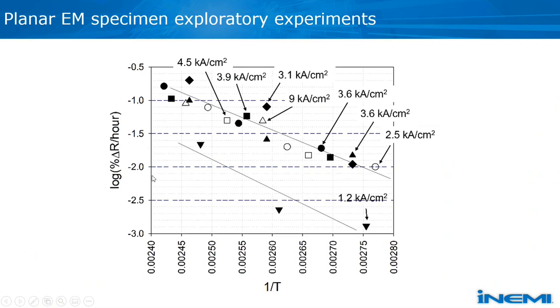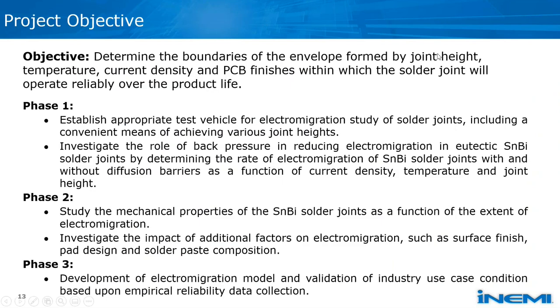So here's the summary of the data. On the vertical axis is the rate of change of electrical resistance versus inverse temperature. You can see this is very well-behaved data. At 1.2 kiloamp the resistance change is low, and at the higher current densities the resistance change is higher. These are just simple exploratory experiments we have conducted, but the actual testing will be done on LGA hardware that Rio is going to describe. So Rio, all yours, please.